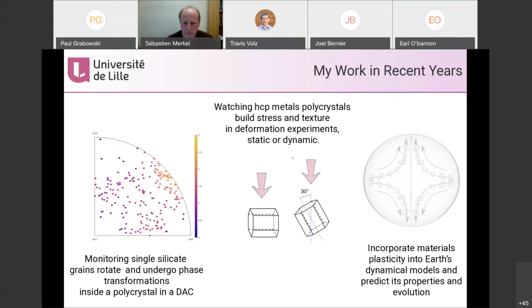And there's a question from Fnu Saranch. The 10-12 twinning mode in HCP is an extension twin. Why do you think it's getting activated during compression? So it is true that 10-12 twinning is an extension twin in HCP iron. It depends on the c over a ratio. When we say extension twin, it's extension of the c axis. And as the figure is projected here, as the shock is coming through the sample, the c axis is perpendicular to the shock, and it's actually under extension. And so you activate an extension twin.